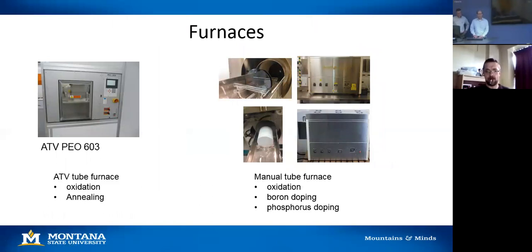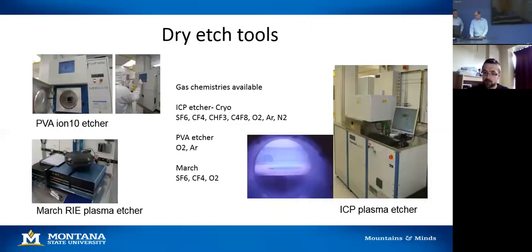So moving on, furnaces, another way, not so much to deposit, you can grow oxide into Si. Silicon basically grows glass on the surface of the wafer. And that's a standard material used for insulation. Besides this one, which is somewhat programmable and computer controlled, we have a manual oxidation furnace, and we have two furnaces for doping, both boron and phosphorus. This supports our class transistors and photovoltaic processes, so you have active devices in this case.